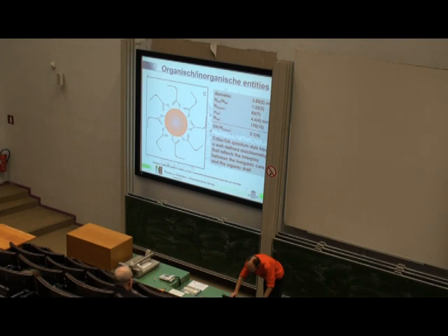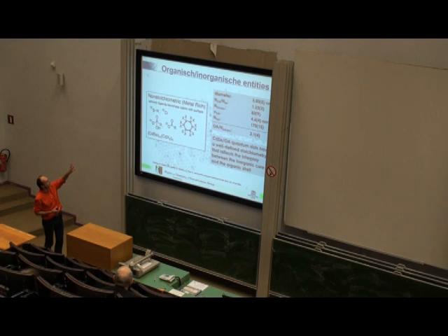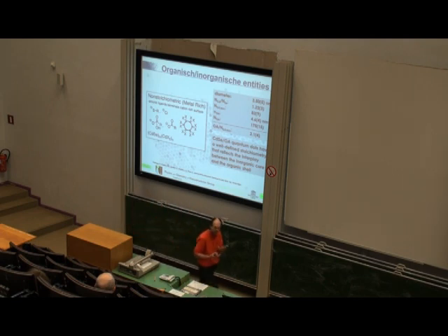That's the chemistry. Let's move to some, well, maybe a last question. We were actually the first to do this, this counting of ligands and excess. It has become a kind of standard, and it has been recovered not just by oleates, but also by phosphonates. Also, if you go to small inorganic ligands, such as chlorides, also thiolates, they all give the same conclusion. The number of ligands that you have is actually such that you just balance the charge on the cations. And it's a very generic picture. It has become a very generic picture of these non-stoichiometric nanocrystals.